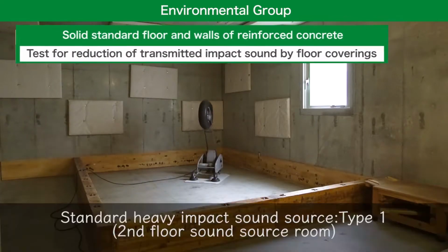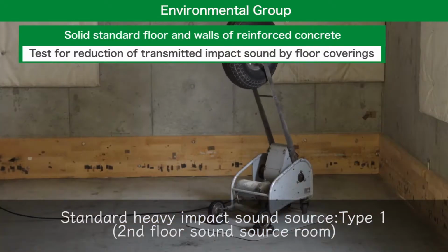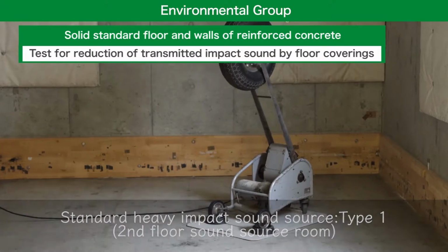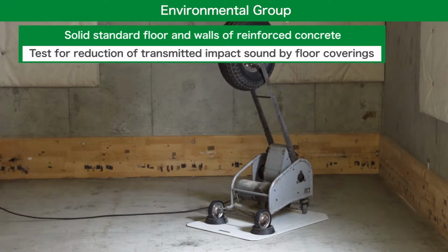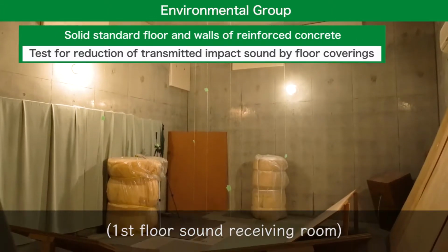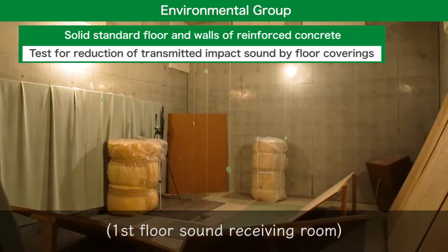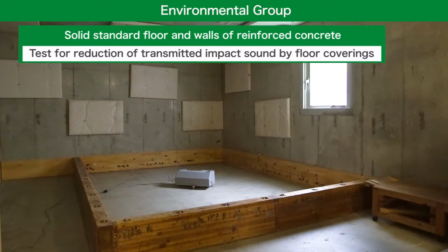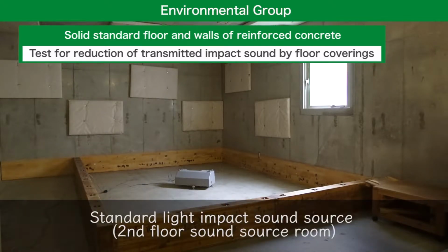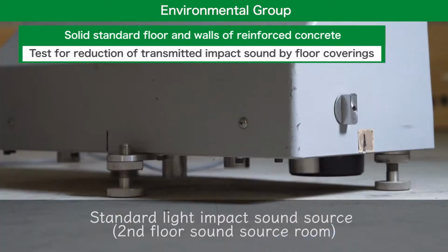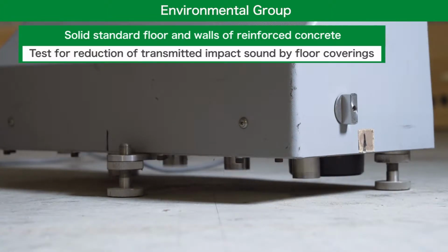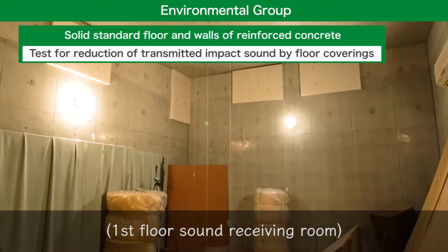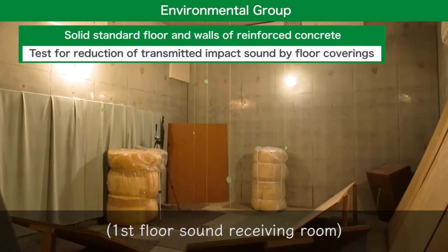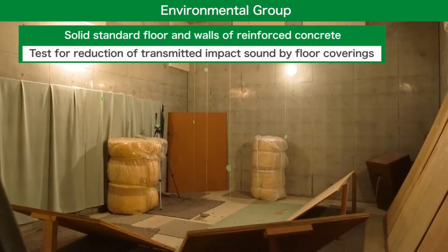A test for reduction of transmitted impact sound by floor coverings is performed by using a sound source room and a sound receiving room of the solid standard floor and walls of reinforced concrete cast together. Impact is then applied to the specimen constructed on standard concrete floor according to the impulsive force characteristics of standard heavy impact sound source on the sound source room side, and the floor impact sound level is measured on the sound receiving room side to calculate the amount of reduction.